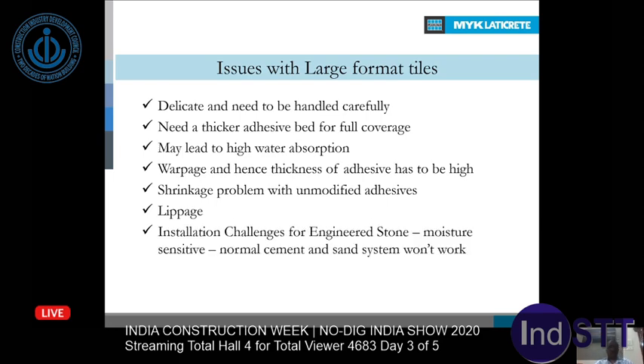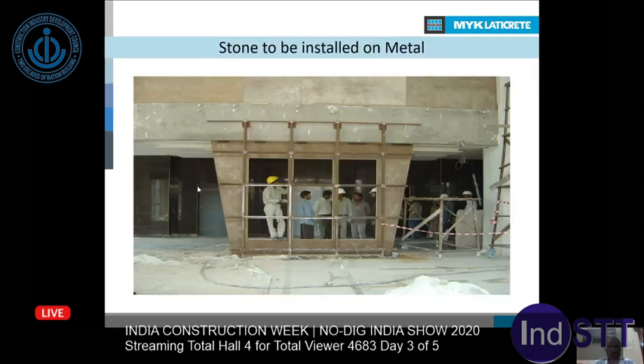So other categories, engineered stone. It almost looks like a natural stone, but it's factory made with resins, epoxy resins, and other additives to make it look like a more natural stone. But it has its own matrix, and that's very moisture sensitive. The moment you fix it with any normal sand system, moisture gets into the stone, then they start warping and bending. Then you lose all the bonding and all the aesthetics and the money you spend on this kind of installation. So you have to be very careful what kind of system you select for installing certain categories.